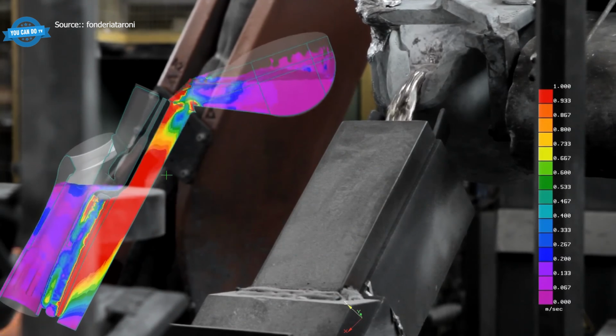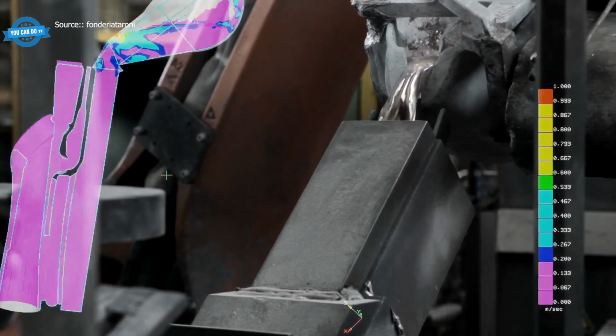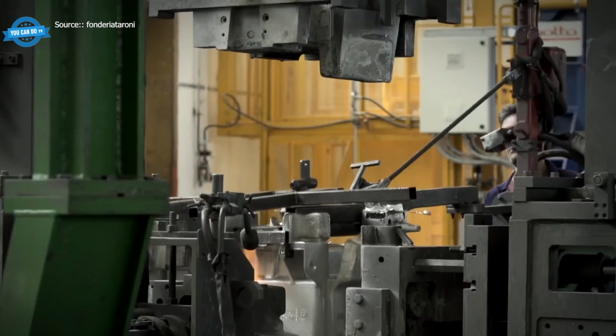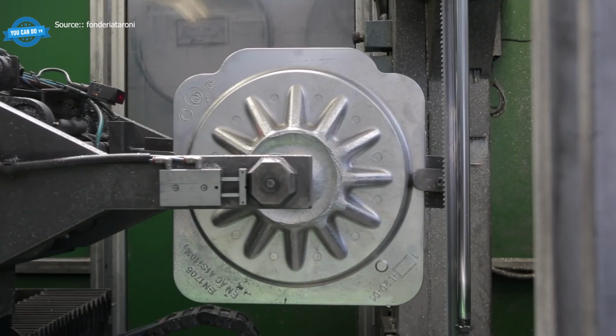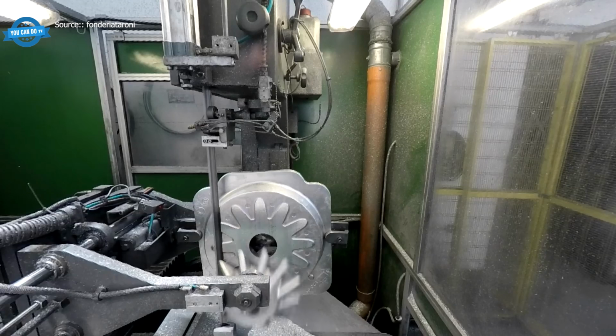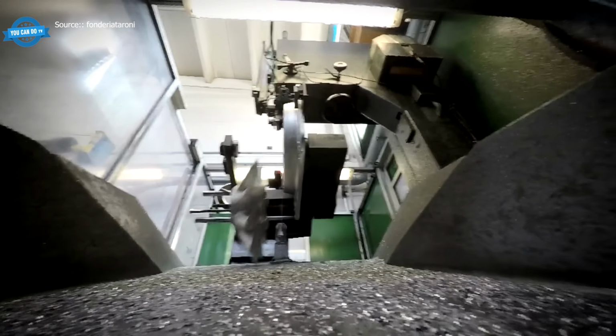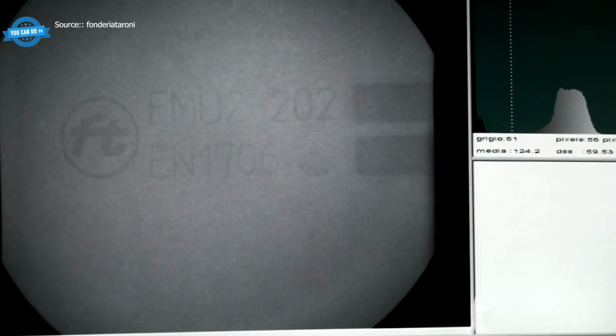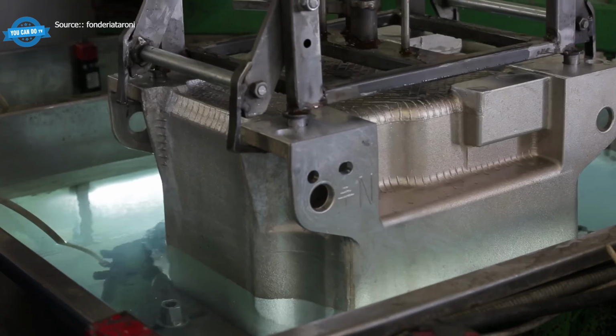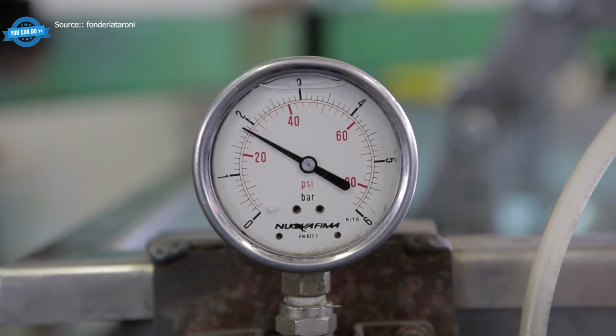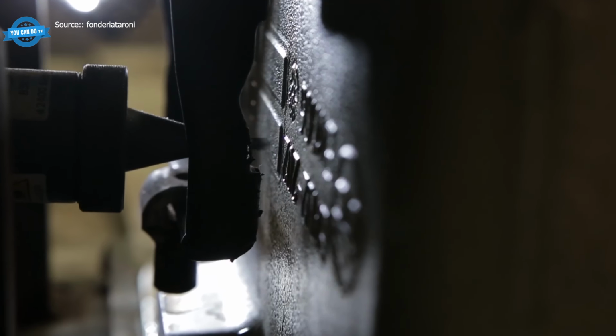Fine grain structure is what turns a decent-looking casting into a part that actually holds up under load. Simulation software models the metal flow before the first pour, so engineers can spot cold shuts and shrinkage voids before they show up in real castings. X-ray inspection catches internal defects after the fact, because aluminum porosity tends to show up exactly where the part cannot afford it.